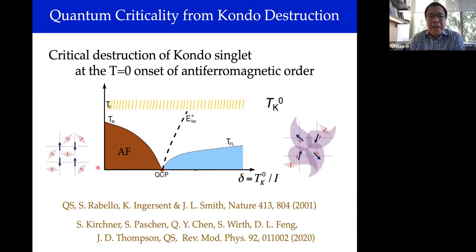But if we get towards the part of the phase diagram which is established by having the local moments communicating with each other, and in this case they form antiferromagnetic order, it would be detrimental to the formation of the Kondo singlet. And if this leads to the destruction of the Kondo effect, and if it happens at the quantum critical point, we have additional excitations that are critical, associated with the destruction of the Kondo effect, marked by this E star scale collapsing to 0 at the quantum critical point.